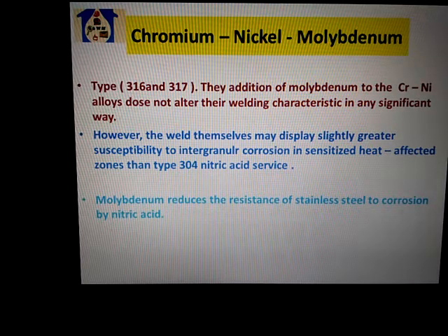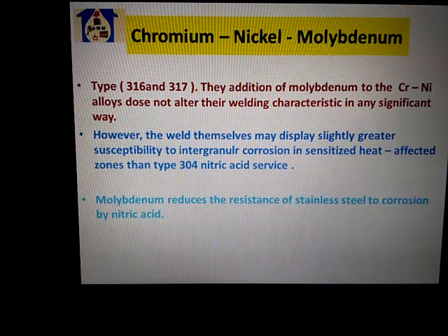Chromium-nickel-molybdenum types 316 and 317. The addition of molybdenum to the chromium-nickel alloy does not alter their welding characteristics in any significant way. However, the welds themselves may display slightly greater susceptibility to intergranular corrosion in the sensitized heat-affected zone than type 304 in nitric acid service. Molybdenum reduces the resistance of stainless steel to corrosion by nitric acid.